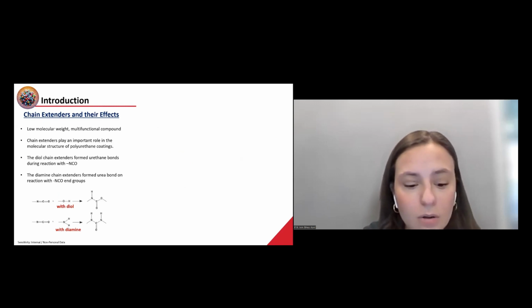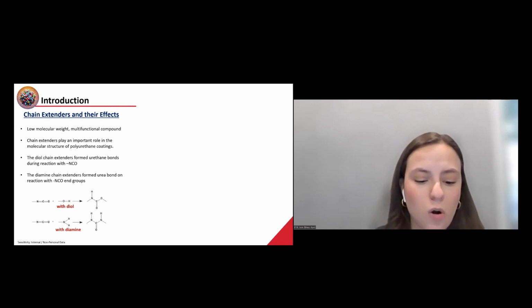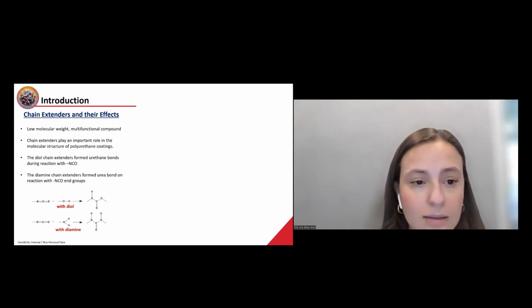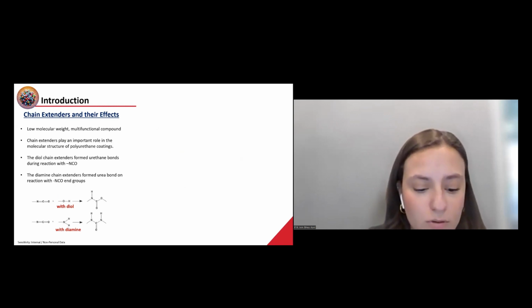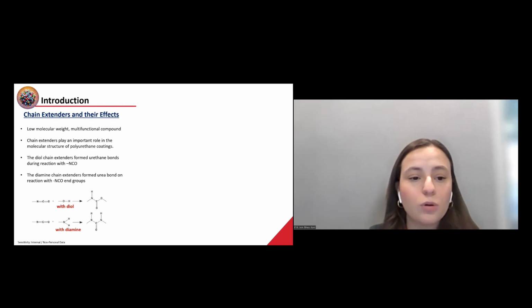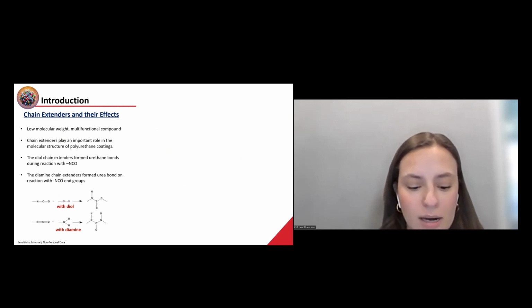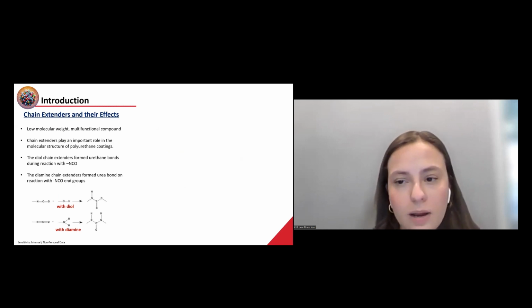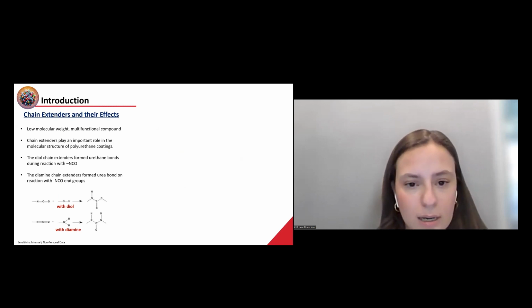Chain extenders are low molecular weight multifunctional compounds that react with the NCO groups of the isocyanates. They play an important role in the molecular structure of the polyurethane coatings. And polyurethane coatings without a chain extender, formed by directly reacting polyol and isocyanates, generally have very poor physical properties.